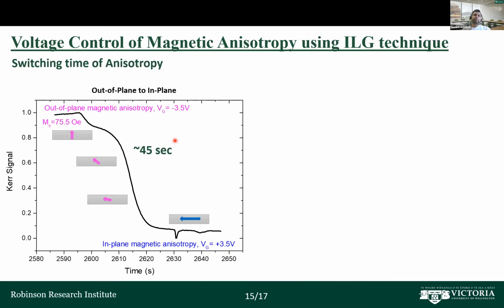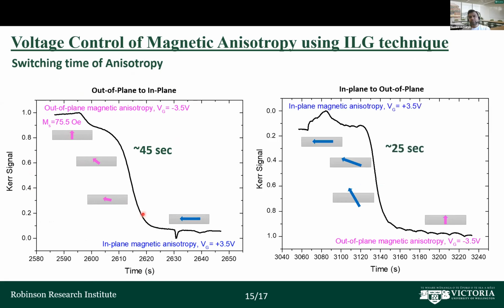To measure the switching time of the anisotropy change, first we saturated the thin film stack in the out of plane direction by applying a saturation magnetic field of 75 oersted. Then we did the time dependent MOKE measurement, and we found that it took almost 45 seconds to change the anisotropy from out of plane to the in plane direction. On the other hand, to change the anisotropy from in plane to out of plane direction, it took almost 25 seconds. So this shows that the out of plane anisotropy is the preferred orientation of our thin film stack.